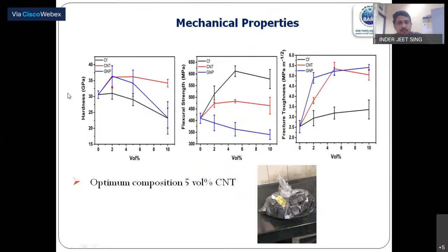Now I want to compare these three materials, and how the mechanical properties of the boron carbide get affected. The hardness reaches a maximum with CNT addition, but with carbon fiber hardness drops. Hardness being a very important criterion for the ballistic application, we need to see which material retains the hardness. Then flexural strength: carbon fiber improves maximum, CNT improves reasonably well, but graphene nanoparticle drops. And fracture toughness improves with carbon nanotube and graphene nanoparticle, but with carbon fiber it doesn't improve that much. So if we optimize, the optimum composition we came up with is 5 volume percent of CNT. As I have already shown, we have the capability of making CNT on a large scale. So this gave us confidence.